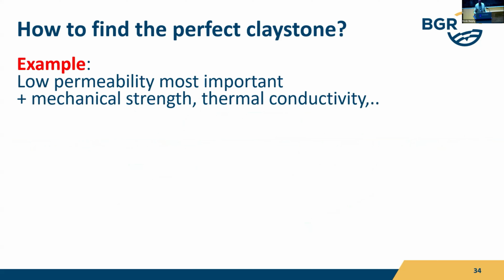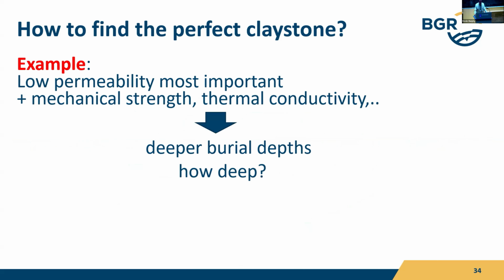Okay, the example would be based on the fact that low permeability is set as the most important parameter. That was defined just. It's not a fact that we think that permeability should be low, right? As well as mechanical strength, thermal conductivity. Why did we put them all together? Simply because they can be fixed at a certain burial depth, right? And how deep should that be?